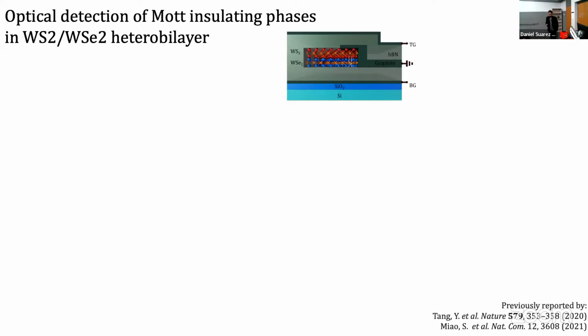Now, the achievement of Mott insulating states has been proved both electrically and optically. Our interests rely more on the optical part. So I'm going to go over a little bit how to demonstrate the formation of Mott insulating states in these materials through optical measurements. We start with the band structure of our two materials, the tungsten diselenide and the tungsten disulfide.